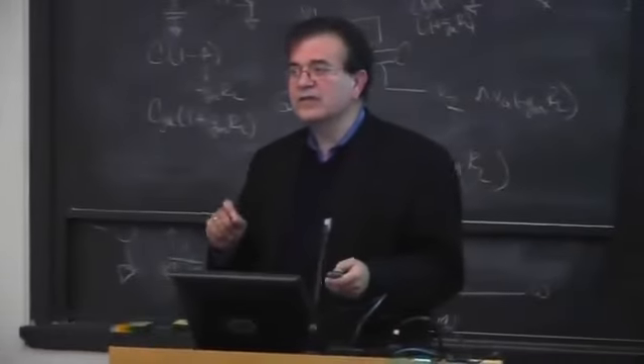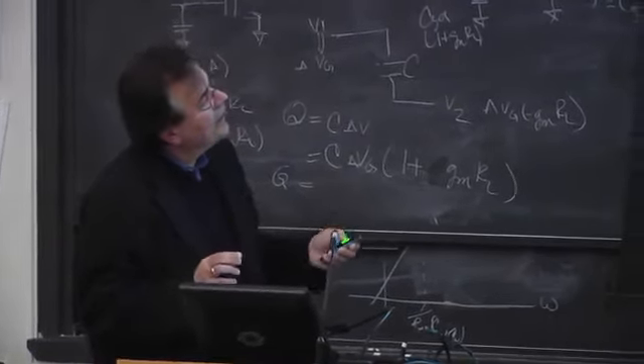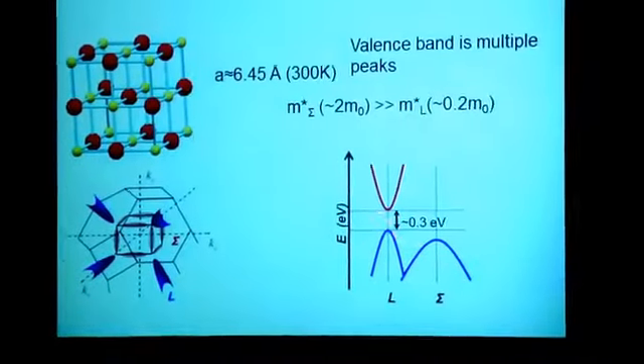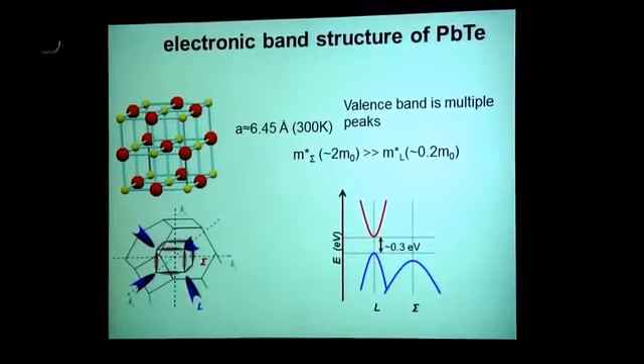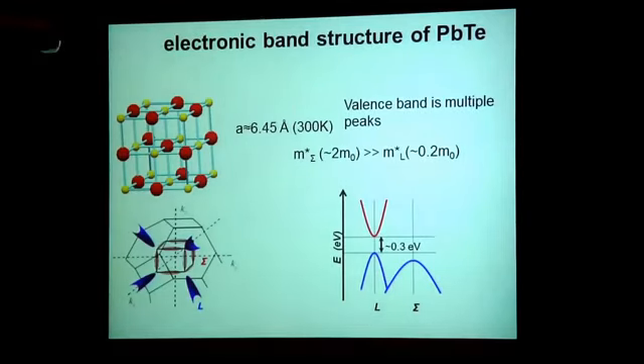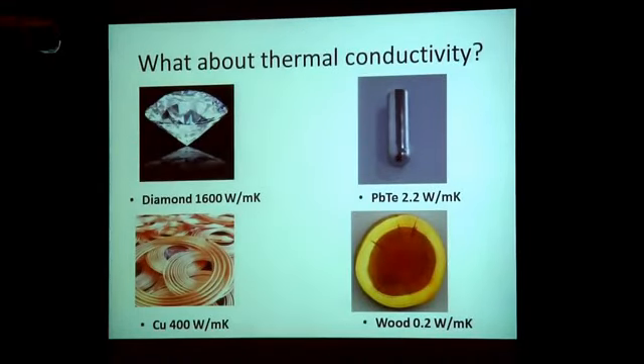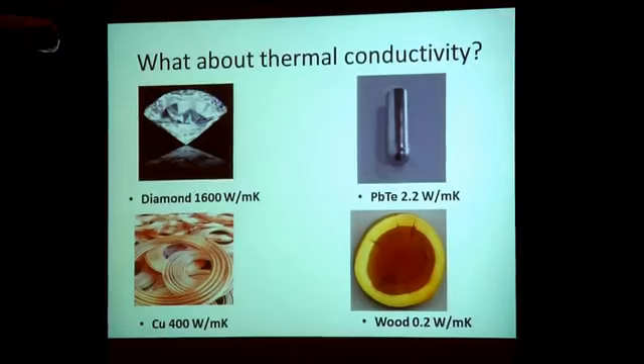And so let's take lead telluride. Lead telluride comes close to the description I gave you with the multiple pockets. It's cubic, so it's very high symmetry. And its band structure looks like this. It has two valence bands and one single conduction band. So when you dope with P-type, you have the potential of actually getting both involved in transport. Band gap is nice and small. And also the multiplicity of these points in the Brillouin zone, the L point and the sigma point, they have high gamma. And so it can give high power factor. So we were looking at this. Let me calibrate you a little bit on thermal conductivity, what we're looking for in thermal conductivity.